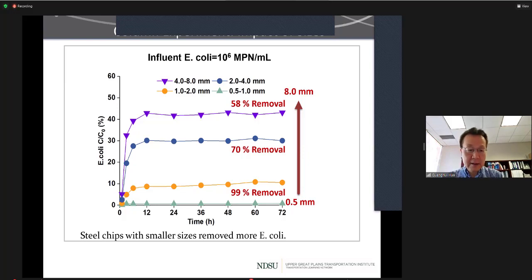And also we learned the removal efficiency was very stable over the 72-hour period, even though there is some early breakthrough between 0 and 6 hours. But after 6 hours, we were able to maintain very stable removal. And the removal efficiency did not decline between 12 and 72 hours. So this result is important, and this can indicate that steel chips are able to maintain stable removal over a long period up to 72 hours.